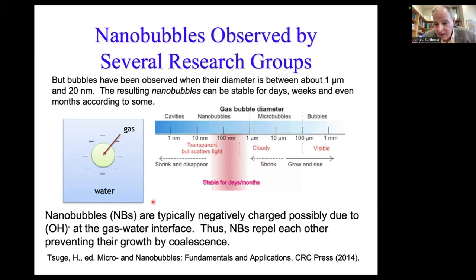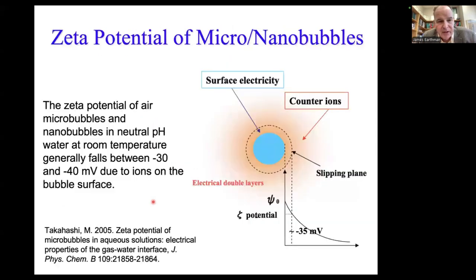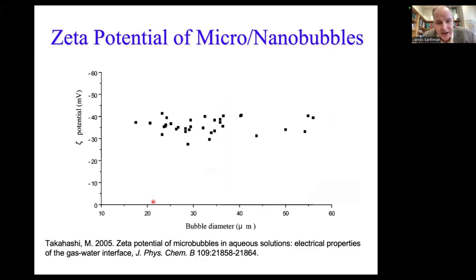Also, what's interesting about the nanobubbles is they repel each other, so they don't coalesce. They don't come together and make bigger bubbles because they're repelling each other, because they're all negatively charged. And a lot of people were reporting this minus 30, minus 40 millivolt zeta potential for them. As a matter of fact, Takahashi, as you can see here, did a study where he measured the zeta potential for smaller and smaller microbubbles, and you can see that the zeta potential doesn't really change in neutral water. It stays within that minus 30, minus 40 millivolt range. That was kind of interesting. Zeta potential doesn't change. Whatever's on the surface of the bubble doesn't seem to be going away as it gets smaller.